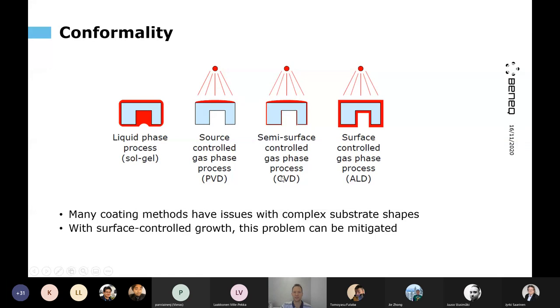And the CVD in general is something a little bit in between. So it's possible, using certain types of process tricks, to get some coating on the backside as well. You still get more on the front side, and it's not possible to coat inside all kinds of smaller features. So that's what ALD really does best.